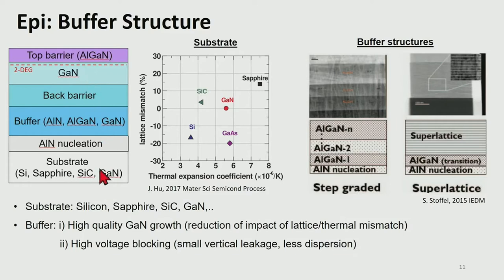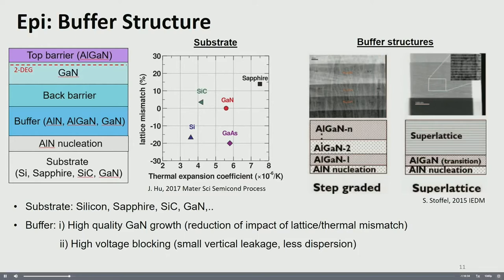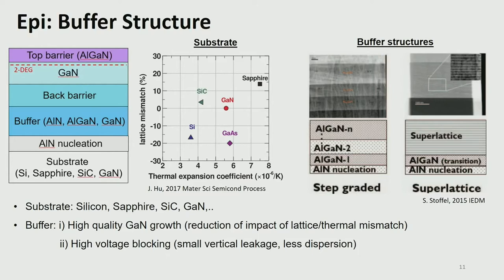If we start from the bottom, first we need a substrate. If you have a pure gallium nitride substrate, it's much easier to grow high quality thick gallium nitride. But unfortunately, there are still many technical challenges to grow a high quality and large scale gallium nitride substrate at low cost. So people typically use a foreign substrate, such as silicon, sapphire, or silicon carbide. And silicon is the most popular choice, especially for power devices, because of its low cost and scalability.